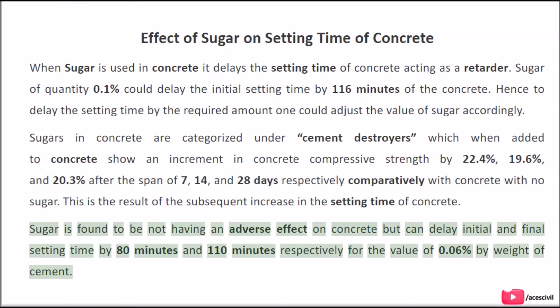Sugar is found to not have an adverse effect on concrete but can delay initial and final setting time by 80 minutes and 110 minutes respectively for the value of 0.06% by weight of cement.